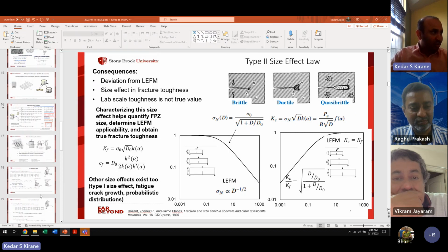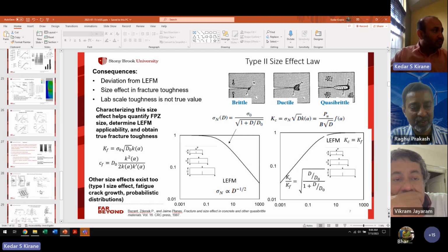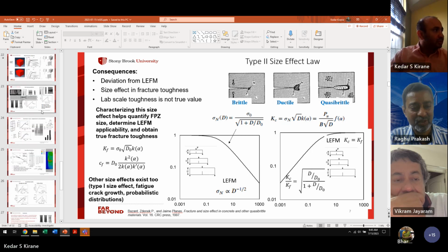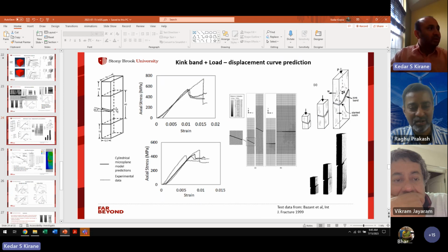So another thing maybe I can show in the slide. These were experiments that we tried to model, right? So they had to create this inclined notch to observe the formation of a kink band. Because when you have compressive failure, there is another mode that can happen, which is axial splitting, but the splitting goes all the way across the specimen. So if you want to isolate the kink band itself, then you have to do some kind of trick to not have that happen.